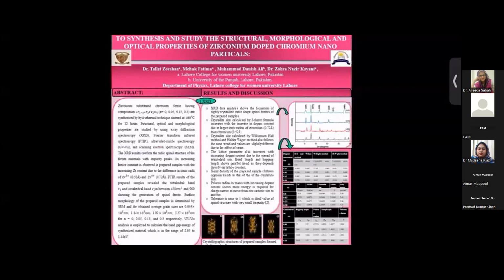The crystallite size calculated by the XRD formula increases with the increase in dopant concentration due to the larger ionic radius of zirconium than chromium. The crystallite size calculated by the Williamson-Hall plot method and the Scherrer method also follows the same trend, and the values are slightly different due to the effect of strain, as shown in this table.